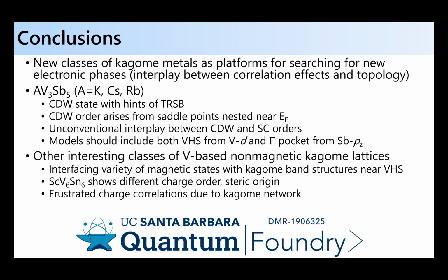And so with that, I'll just finish and maybe allow for some discussion. We think that there's new classes of kagome metals, as Joe mentioned in the beginning of the conference, with flat bands that are promising platforms, but also looking at fillings near these Van Hove points that can drive seemingly complicated or very interesting electronic states. The 135 class of vanadium-based compounds seems to show a charge density wave state that's very complicated, with hints of time reversal symmetry breaking. The onset of charge density wave order relies on these saddle points being near the Fermi level, but it also probably relies on these antimony states being at the gamma point.